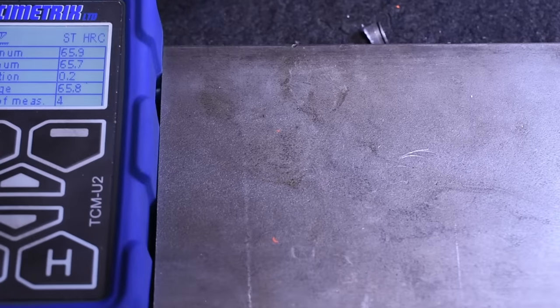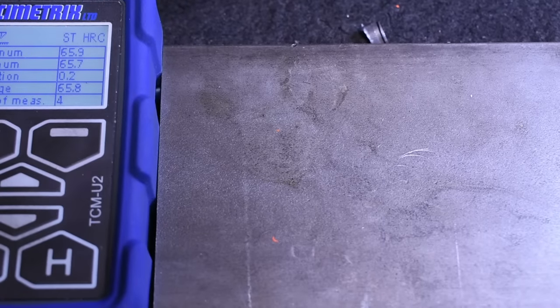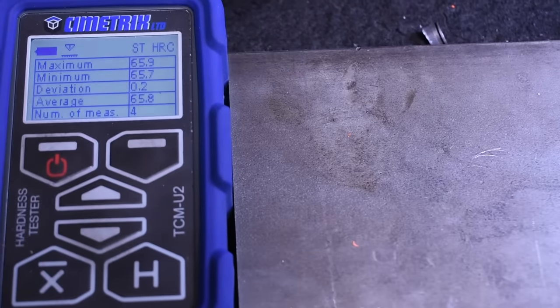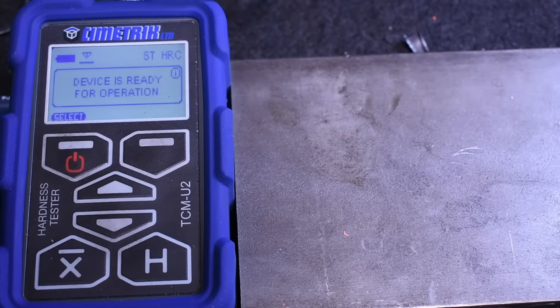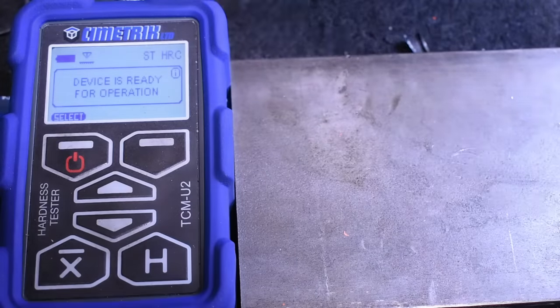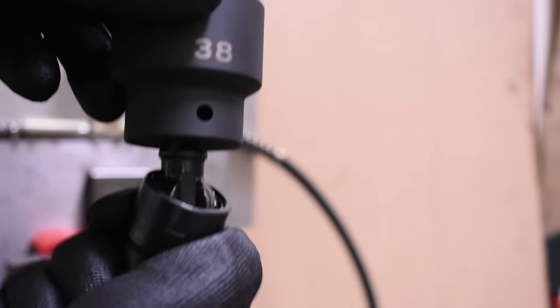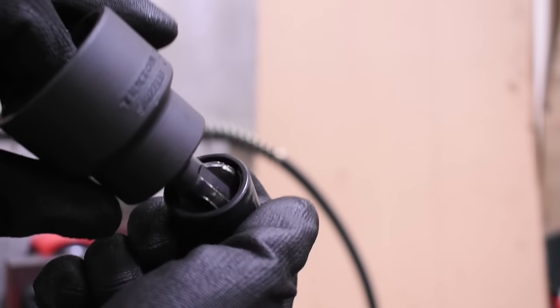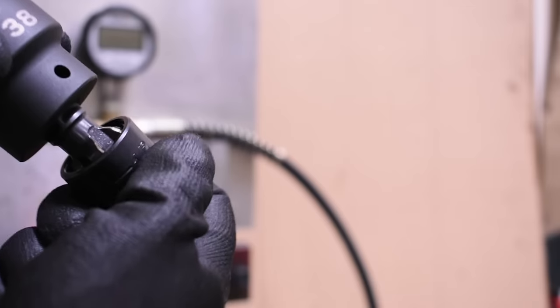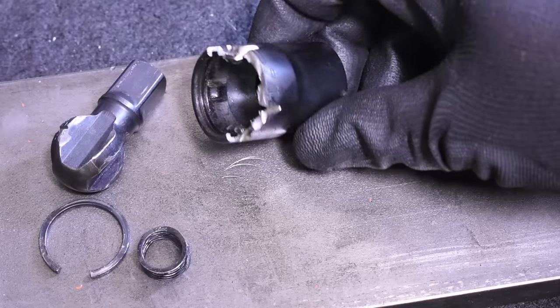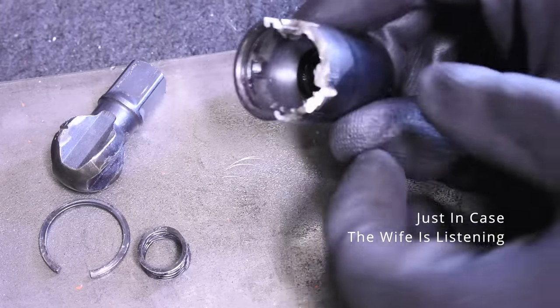A good Japanese chef's knife in your kitchen might be sixty two to sixty four RC, but sixty five point eight? That's well above the ASME spec of fifty five, and we can't think of one reason you would need almost any tool to be this hard except maybe a scribe. It also might explain why these tiny drive tabs look fine, while as the lobes on the socket drive end, which are a full twenty points softer, look like Rocky after twelve rounds with Ivan Drago. Although we're surprised to see the tabs didn't shear off completely at that hardness, as hard doesn't always mean good.